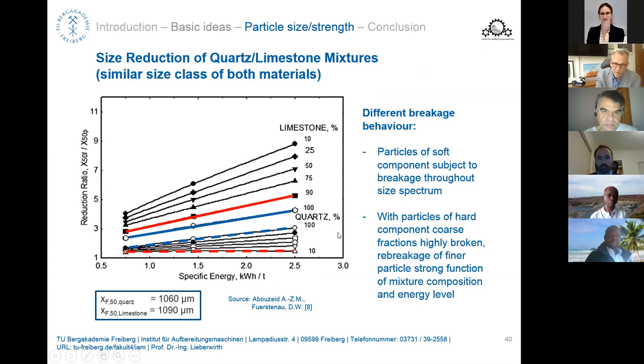Another important aspect which was investigated already is the different strengths of the particles. I think that is one of the key publications in this field I'm quite often referring to, from Abouzeid and Fuerstenau, published in 2009. They used limestone and quartz, almost same size as you can see here, 1060 microns F50, and limestone 1090 microns. And he was investigating how the comminution occurs. And here we see in this shape the reduction ratio of the different fractions under a certain mixture status.